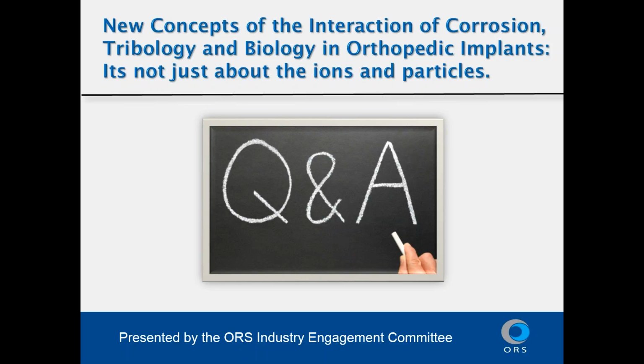So it is potentially a model to pursue to look at the so-called pseudotumors or adverse local tissue reactions as being driven not so much by the ions per se, but perhaps by the oxidative burst molecules that are being generated, or indeed by a combination of the two, where not only iron serves as a Fenton reaction catalyst, but cobalt and chromium ions can also serve as such a catalyst. So creating much higher concentrations of hydroxyl radicals, for instance, in the presence of these cations. So I think it's really maybe a combination of the presence of high levels of ions and these oxidative burst byproducts that are reactive oxygen species that can lead to damage of the soft tissue and perhaps damage of the bone as well.